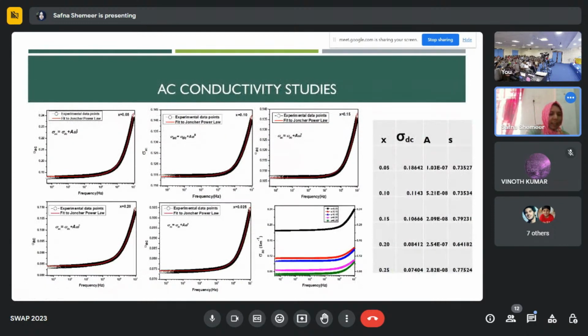And the AC conductivity is also studied. The AC conductivity is independent of frequency at lower frequency region and increases with high frequencies. Here, the sigma AC is calculated using Jonscher's power law, and according to JPL, the frequency independent plateau region is attributed to DC conductivity. And this is possibly due to the short range pairwise hopping between the neighboring particles.